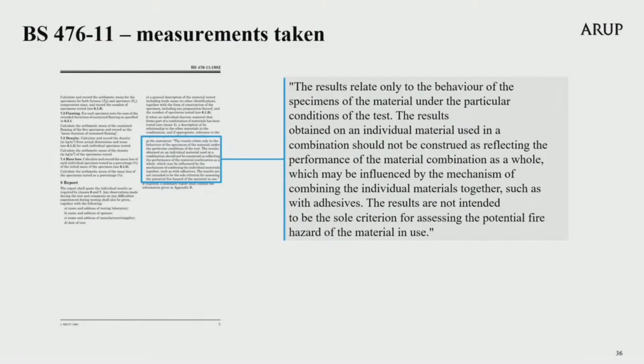It is a requirement of the test report that the following text is stated. The results relate only to the behaviour of the specimens of the material under the particular conditions of the test. The results obtained on an individual material used in a combination should not be construed as reflecting the performance of the material combination as a whole, which may be influenced by the mechanism of combining the individual materials together, such as with adhesives. The results are not intended to be the sole criterion for assessing the potential fire hazard of the material in use. This is the important test for materials of limited combustibility, noting no evidence of such a test has been submitted to the inquiry at this time.